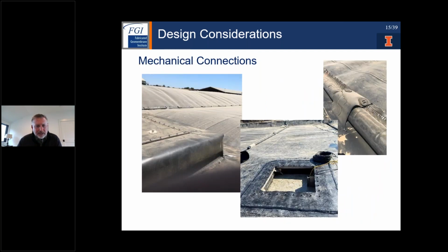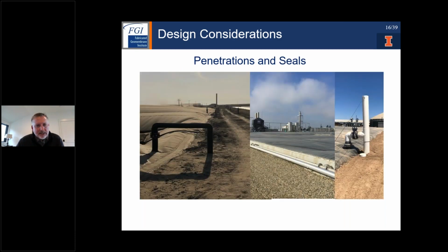Next slide, please. Just talking a little bit about mechanical connections. There are many access hatches, mixing hatches, and welds of the ballast system to the cover. You want to make sure that the tension being carried by that cover can also be carried by any mechanical connections to the cover. Otherwise you have an issue with potentially higher localized stresses in these regions around these mechanical connections. So you just want to make sure you take that into account in the analysis of the cover system. Next slide, please.